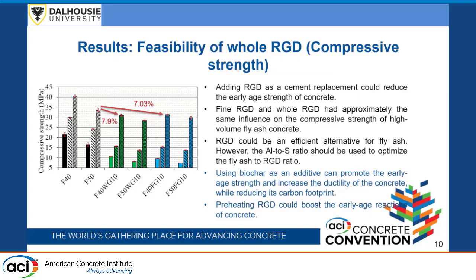But the main issue right now is the low early age strength of the system compared to what we have for F40. So we go to examine the effect of biochar. If you were in the biochar session, they used the powdered biochar, but we use the whole biochar because of its potential to provide water. So it acts as a water reservoir for internal hydration and can promote the early age strength of the system. It can also increase the ductility of the system. And it's important for us because by adding recycled gypsum drywall, we actually increase the brittleness of the system. So we need more ductility, which could be provided by the biochar, and we also reduce the carbon footprint of the system.